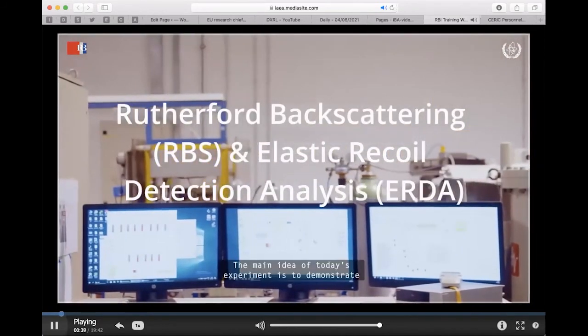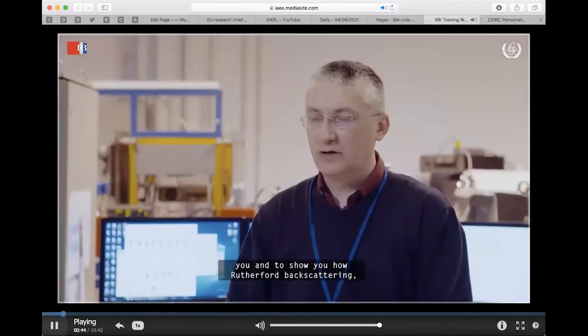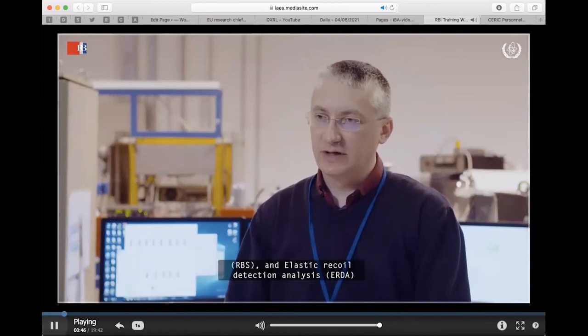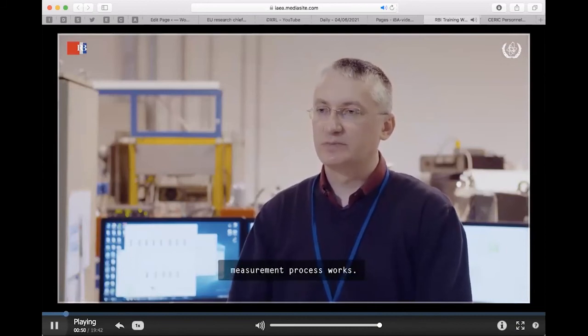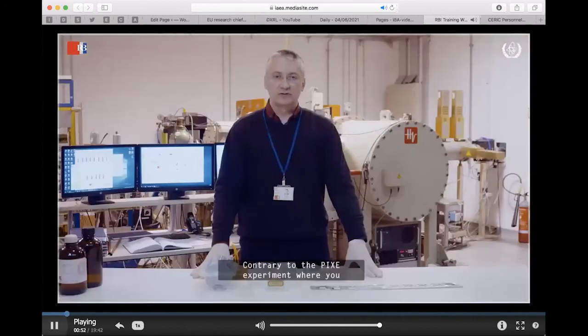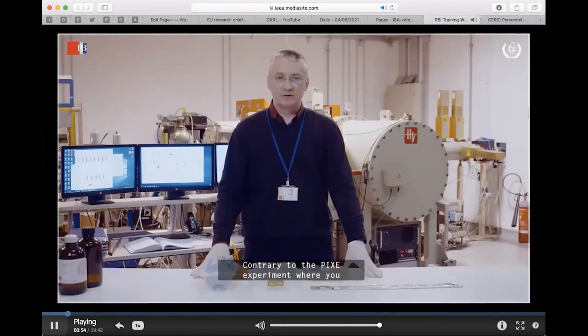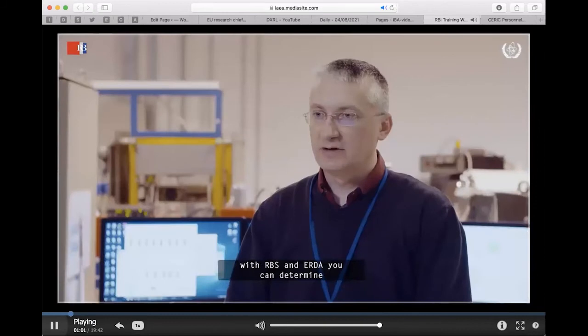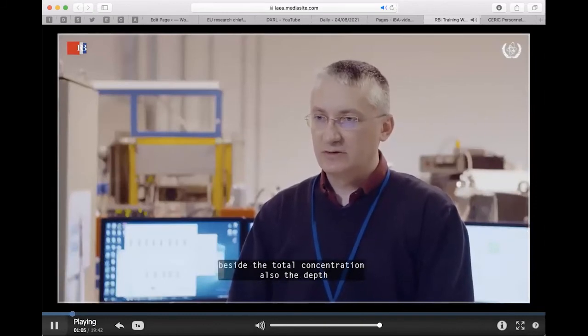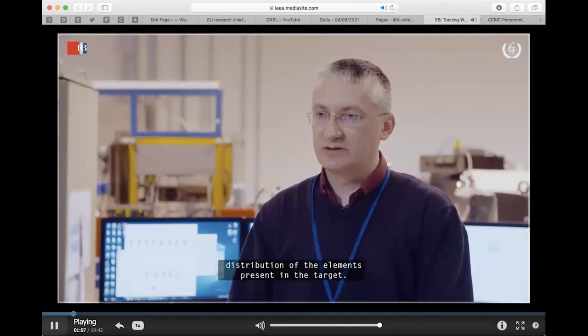The main idea of today's experiment is to show you how the Rutherford backscattering, RBS, and elastic recoil detection analysis, ERDA, measurement process works. Contrary to the PIXE experiment, where you saw that you can calculate the total amount of material present inside the target, with RBS and ERDA you can determine, besides the total concentration, also the depth distribution of the elements present in the target.